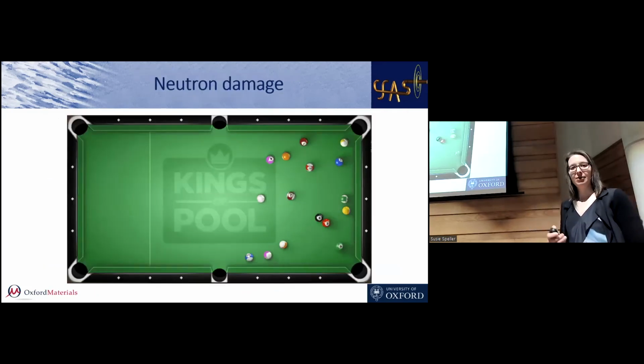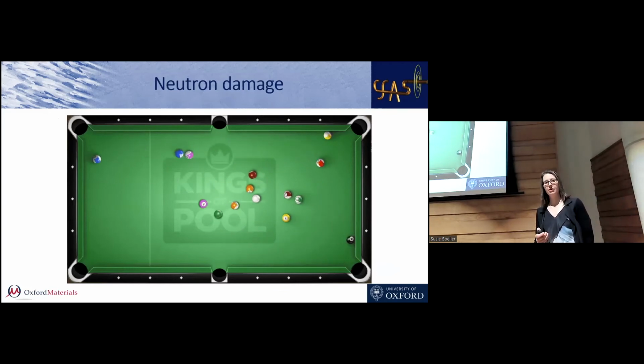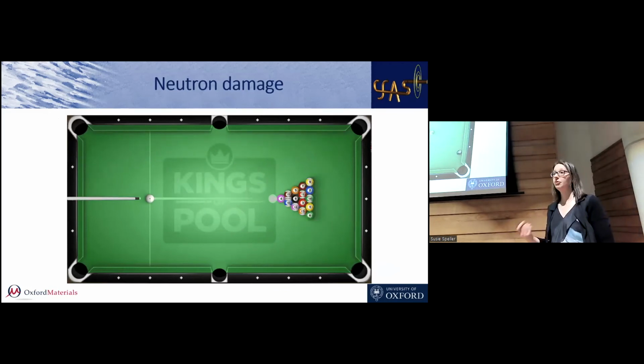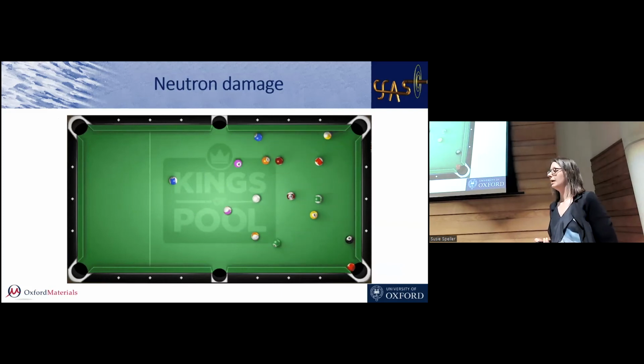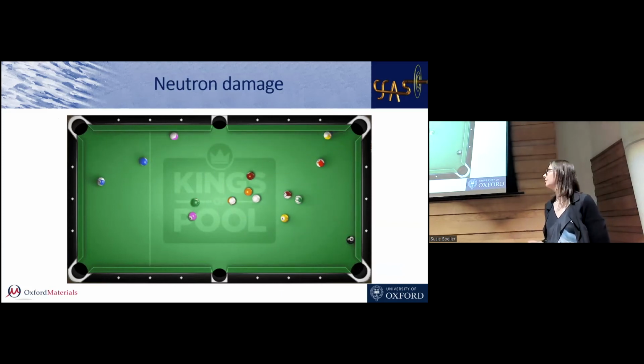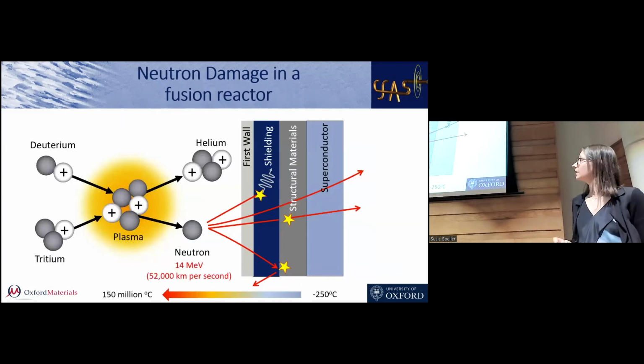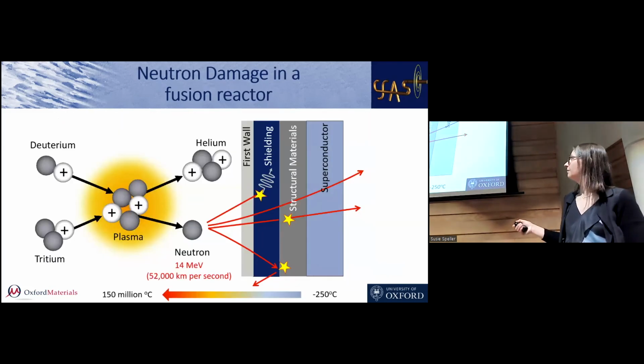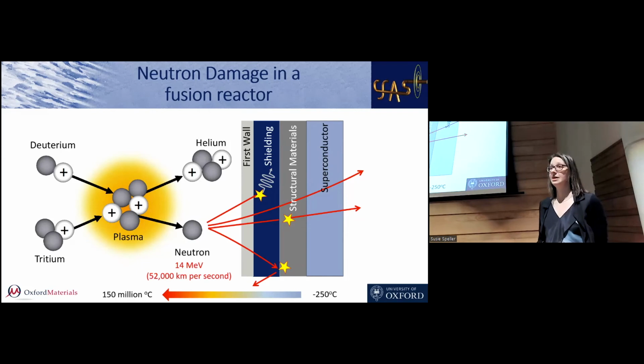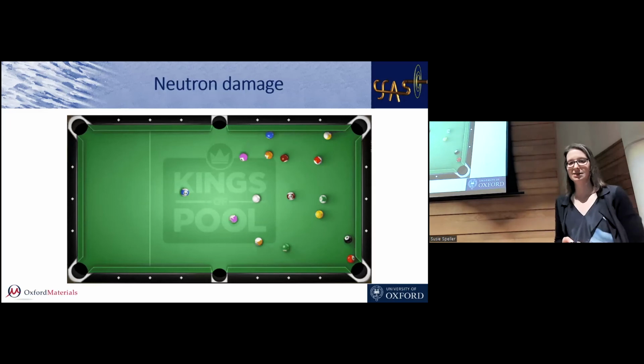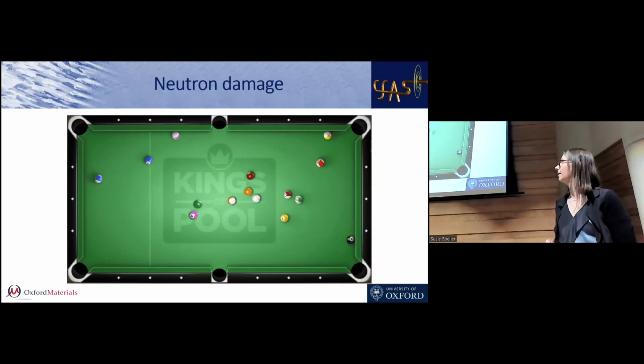So I'm going to run out of time, unfortunately. So I'm going to talk for a couple of minutes about neutron damage. So in a fusion reactor, we have a very harsh environment because not only do we have this very high temperature, but very soon, a very small distance away, we've got our superconductor, which is now at minus 250 degrees C, so a big temperature gradient. But these neutrons move and they get through everything and they knock into our material and they damage it. So what they do is they hit the atoms inside the material and they move everything around like that.